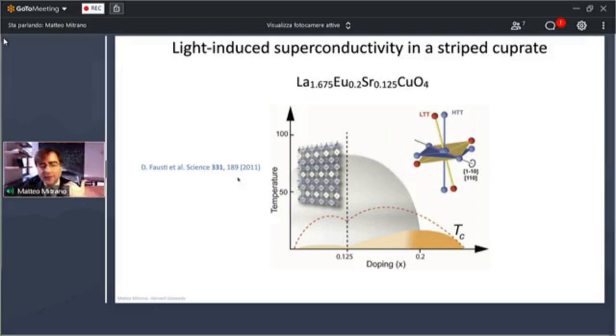of the copper oxygen octahedra, which led to the observation of enhanced superconductivity out of equilibrium in a material, LESCO, where superconductivity at equilibrium is quenched by the presence of so-called charge order. And I will come to this phase later in the talk. But essentially, you have the doped holes that should conduct electricity in these materials tend to self-organize in stripes, in metallic and insulating rivers, therefore quenching transport. And superconductivity doesn't occur naturally. By distorting the lattice, these researchers were able to show transient signatures of superconducting coherence seen as tunneling along a certain crystallographic direction.